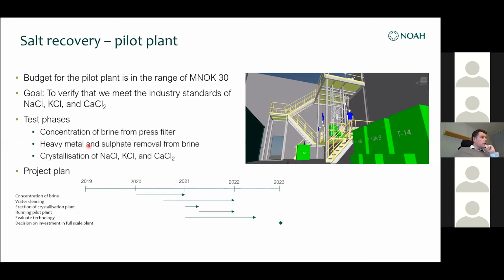The next one is cleaning the brine before it enters the crystallization plant. Heavy metals: since we can control the pH of our gypsum and our brine, the heavy metal content is very low. But as you may know, if you have been working with fly ash, you have a lot of sulfate in it, and the solubility is fairly high. So we are now working on how to reduce the sulfate concentration and at what level is needed, which is the target. We don't know yet.